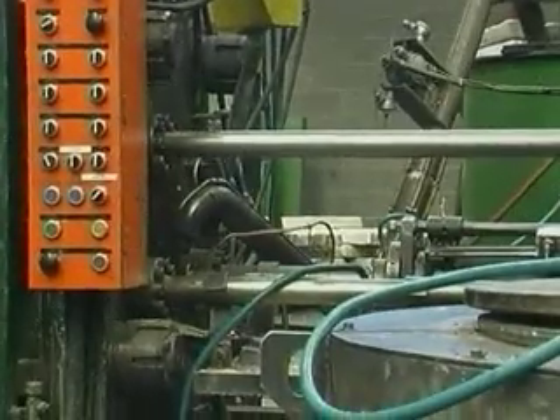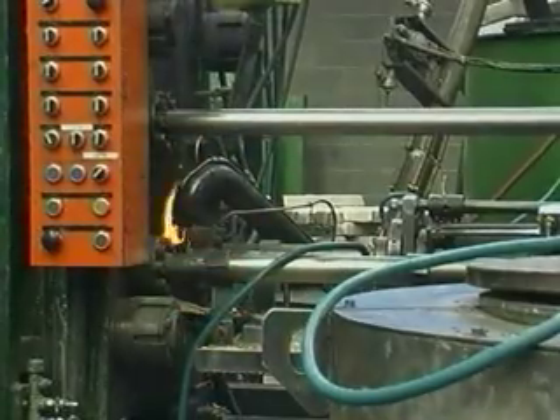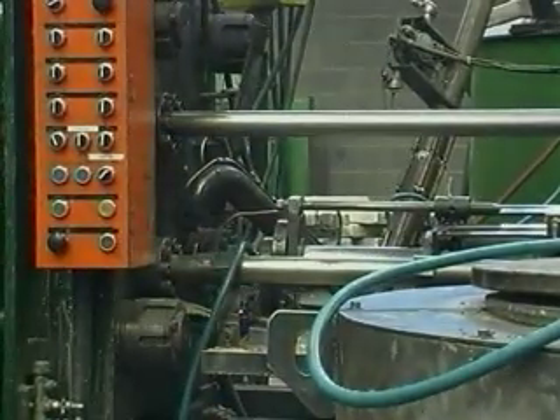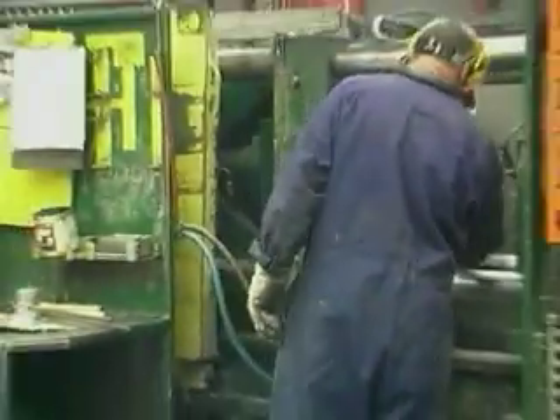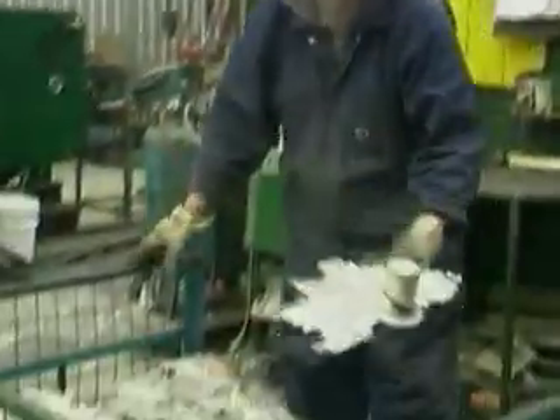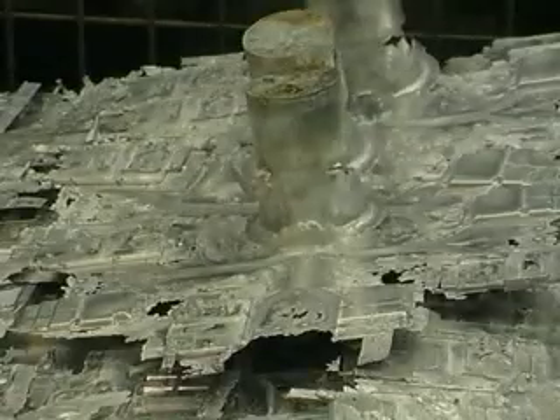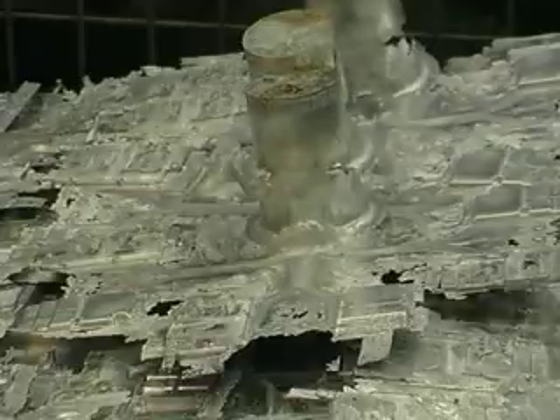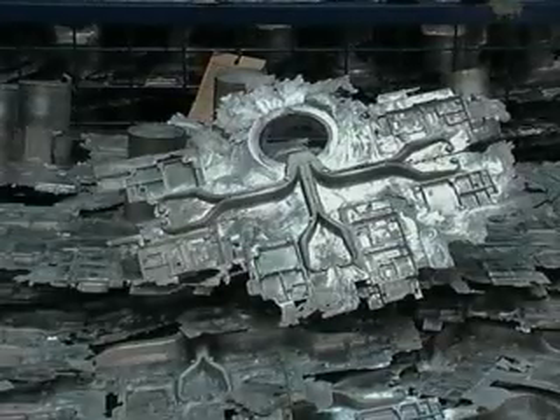A sealed siphon delivers the molten magnesium alloy into the cold chamber. The piston forces the metal into the die. It solidifies and is pushed off by the ejector pins. 6 components are made with every shot. With a wall thickness of only 0.4 of a millimetre, the casting is checked against a strong light for any defects. The extensive flashing is partially due to the high fluidity of the magnesium alloys.